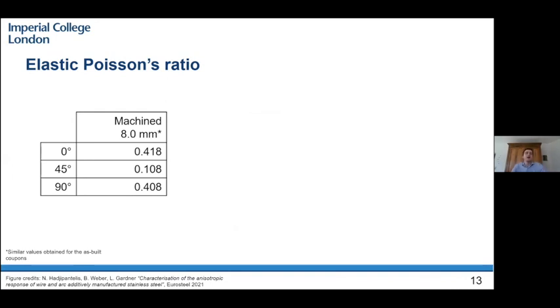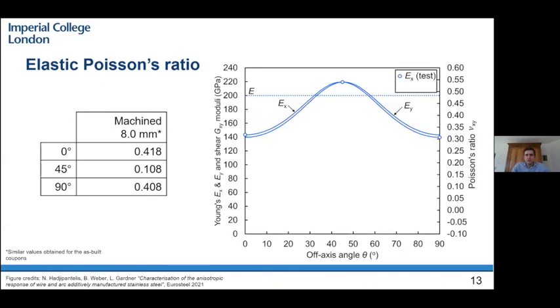Coming to some results. For the elastic Poisson's ratio for the 8mm machined coupons, you can see that they are rather similar for the 0 and the 90-degree direction, but vastly different for the 45-degree direction, which again comes from the orthotropic material behavior. We can predict how this one would behave with theoretical curves that are fitted to the Young's moduli evolution over the different off-axis loading angles. So in the blue thick curve, you can see how EX and EY are evolving over the different angles. From this, we can then determine how the Poisson's ratio would evolve.